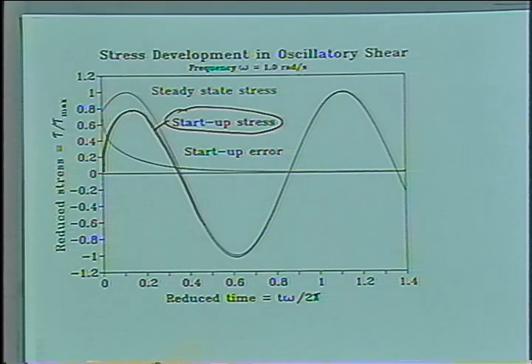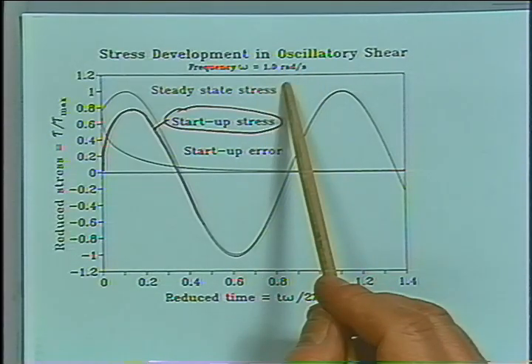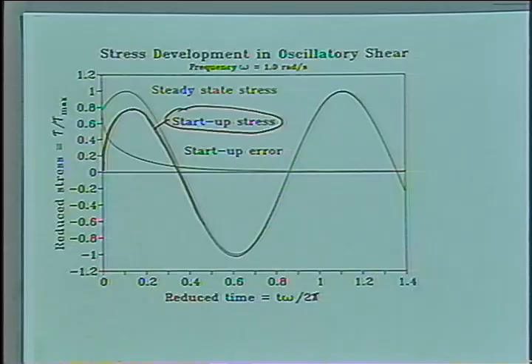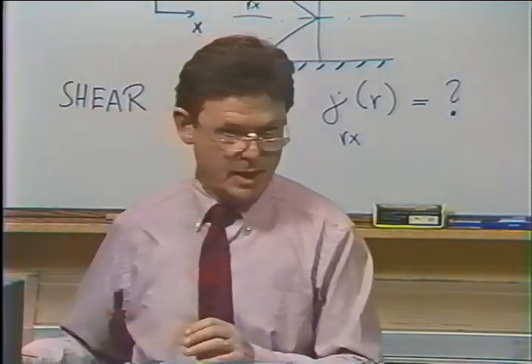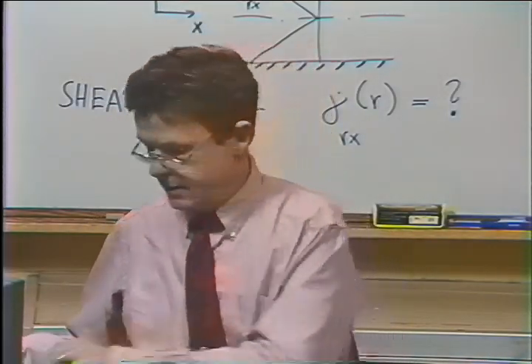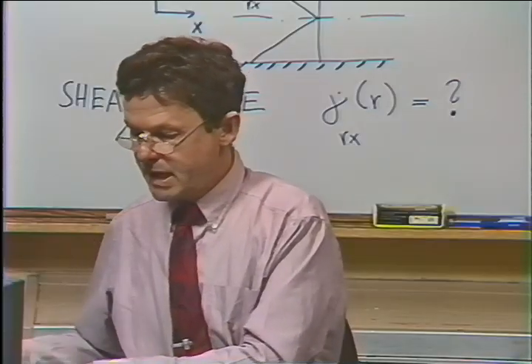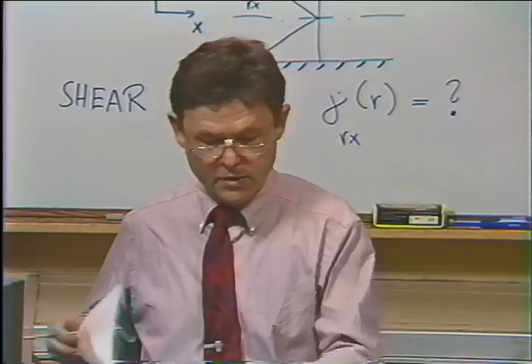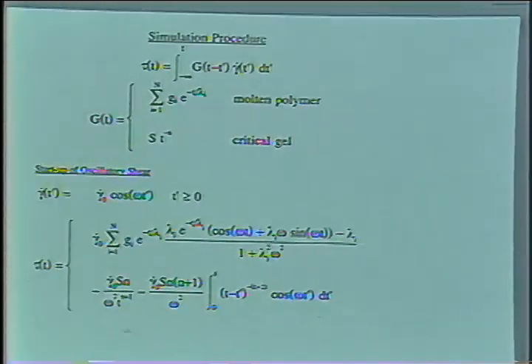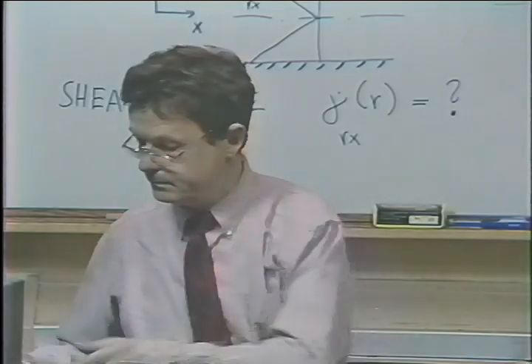Now, in our calculations, we used a period in the order of a second and used a sample which had a relaxation time of an hour about. And you can see that the relaxation time of an hour doesn't disturb our experiments. We really can probe short times in that experiment if we choose low frequencies. And that's one reason why this experiment is so popular, is so powerful for analyzing data. In your handout, you have the equations which are used for calculating the startup. It's a straightforward exercise which you might want to go through.